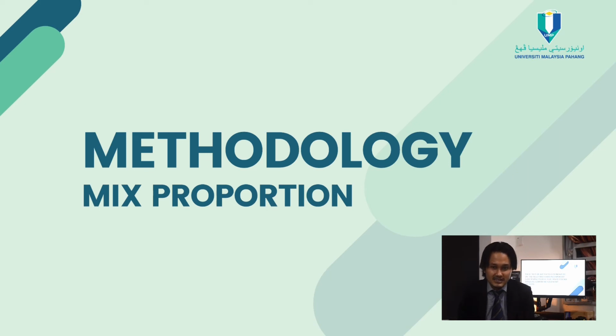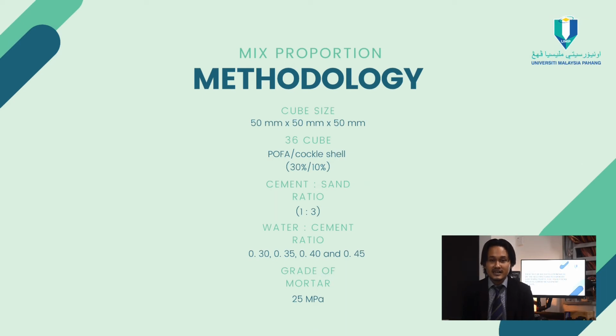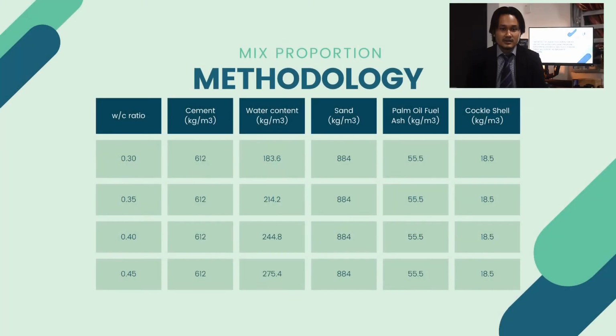For methodology, the mixed proportion: the cube size that I will use is 50 mm, and the sample is 36 cubes, containing 30% of POFA and 10% of cockle shell. The cement sand ratio is 1:3, and the water cement ratio that I will use is 0.3, 0.35, 0.4 and 0.45. And the grade of mortar is 25 megapascal.